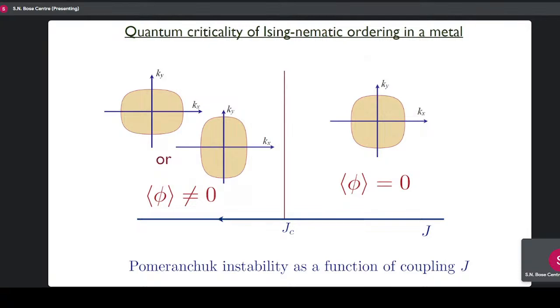So the Fermi surface has the full symmetry of the square lattice. Then you crank up some interaction, which I'm calling J here. And when the interaction is strong, the system likes to break the symmetry and distort into a rectangular shape. Structurally, this is just the usual tetragonal to orthorhombic phase transition that's seen in numerous crystals. But here, the idea is that it's driven not by the structure, but by the electrons. So although symmetry-wise it's just tetragonal to orthorhombic, the physics here is the interaction between the electrons that is driving this kind of structural transition.